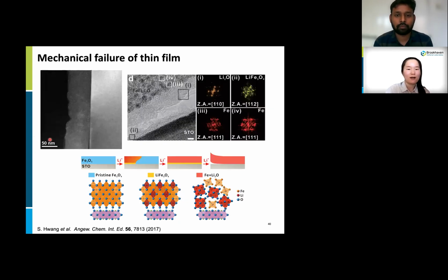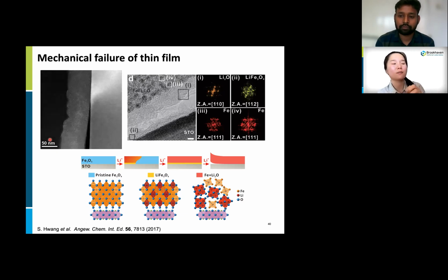When more lithium ions are introduced here, the conversion reaction eventually happens at the interface, and because of additional strain from the volume expansion, the thin film is finally detached from the substrate. From this work, we can learn that strain is an important factor to determine the reaction kinetics. And also, if we control the strain, it might be beneficial to use electrode materials that undergo huge volume expansions.